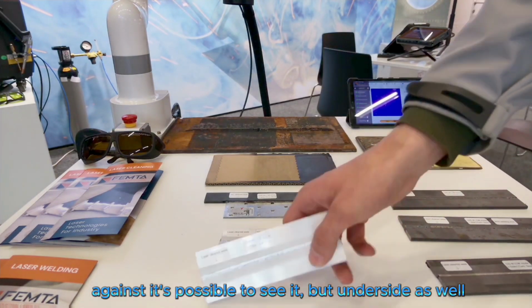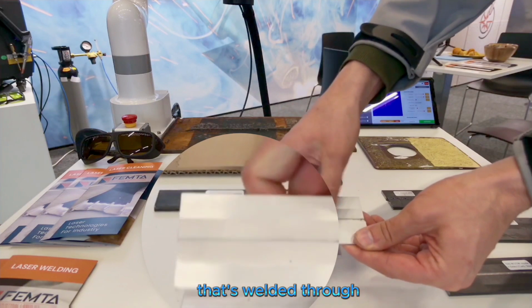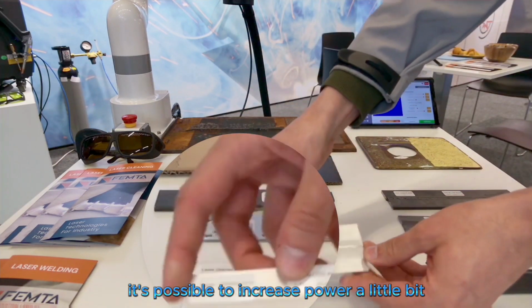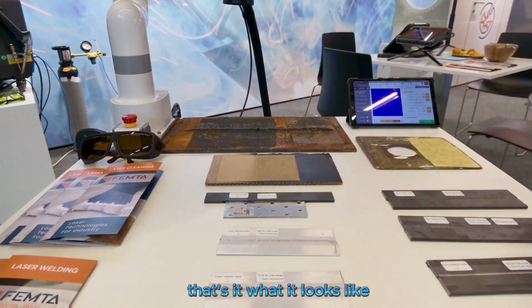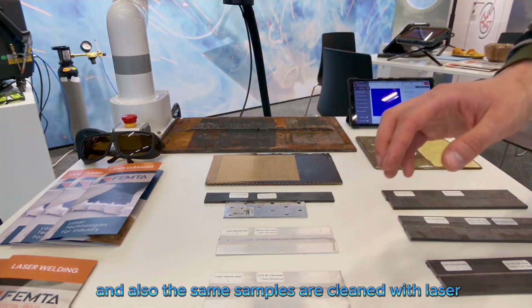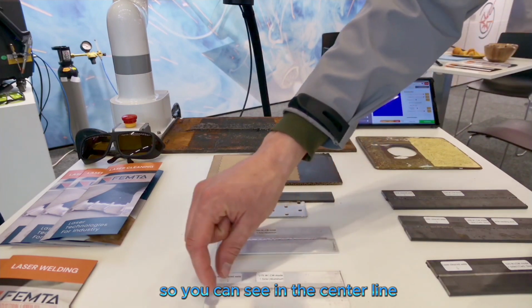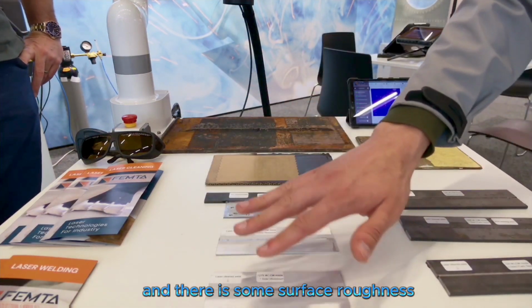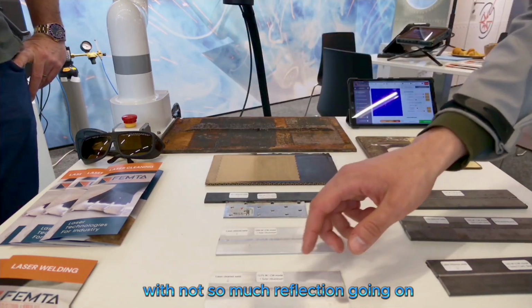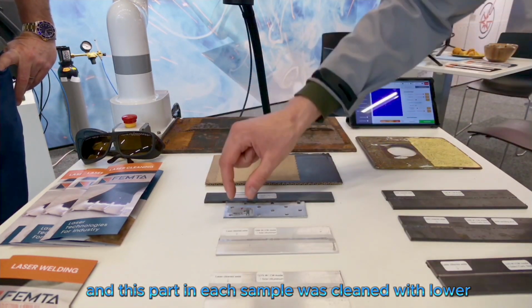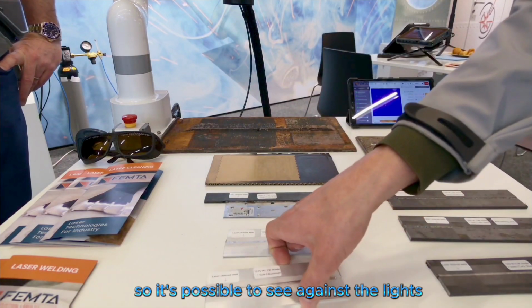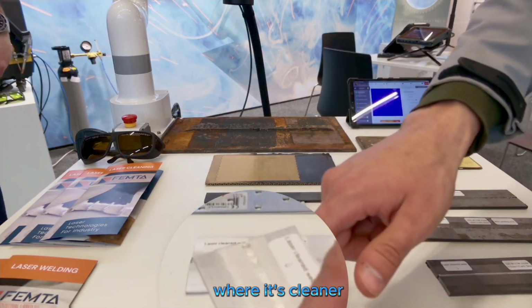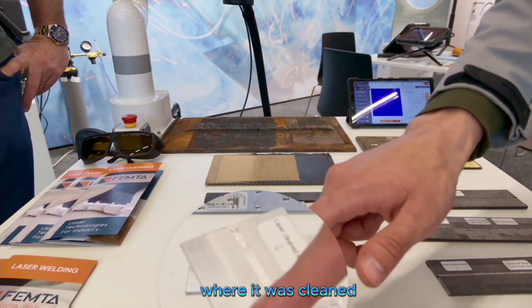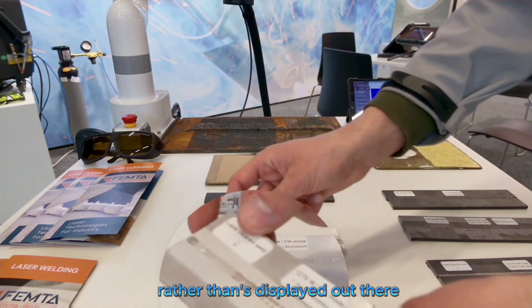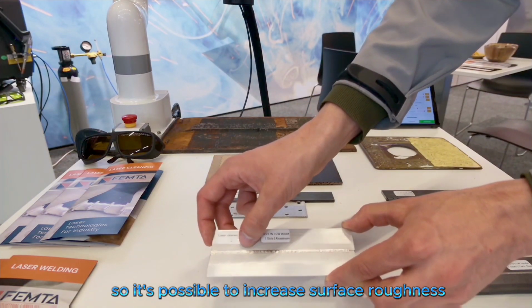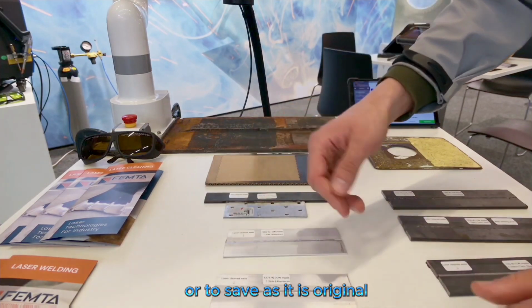It's possible to see the underside as well, that it's welded through. Not fully, it's possible to increase power a little bit, but this is what it looks like. And also the same samples are cleaned with laser. You can see in the center line, it was cleaned with high power, and there is some surface roughness with not so much reflection going on. And this part in each sample was cleaned with a lower power setting. So it's possible to see against the light that it's cleaner where it was cleaned. So it's possible to increase surface roughness or to save the surface as it is originally.